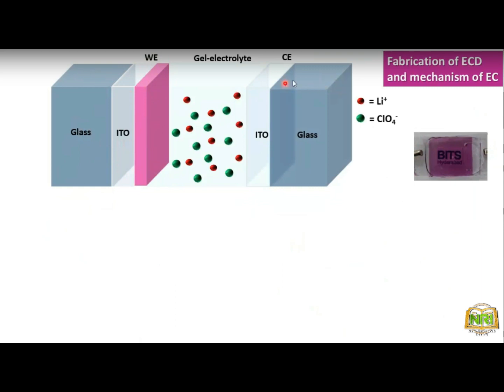Now, another electrode we have taken is normal ITO glass, with no coating of any kind of material, so that will act as the other electrode. Now, obviously to transfer the electron, there should be some electrolyte, which is a jelly electrolyte, where the cation is lithium plus and the anion is perchlorate ion. The main thing is that this kind of electrolyte should be an ion conductor, not an electron conductor. This is the normal condition where the fabricated device looks like that: simple ITO with the film on it, then the gel, then another ITO, in a sandwich kind of structure.